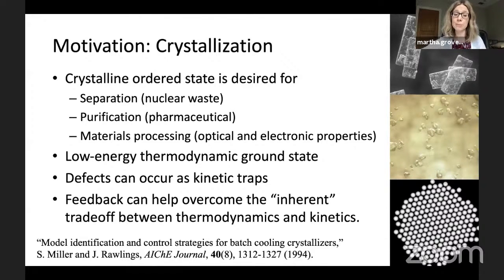So if we'd like to assemble the system into a crystalline state very rapidly, then we might get defects. If we go slower, we can approach the low energy thermodynamic state. And so with feedback, we can potentially see defects as they're forming and take intervention only when needed, and then potentially get much faster to the ordered crystalline state through feedback.